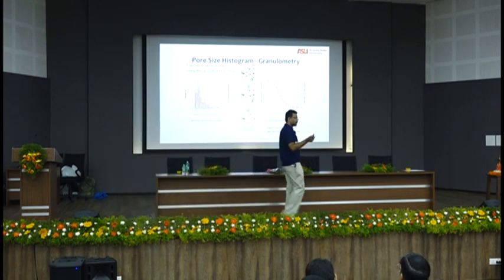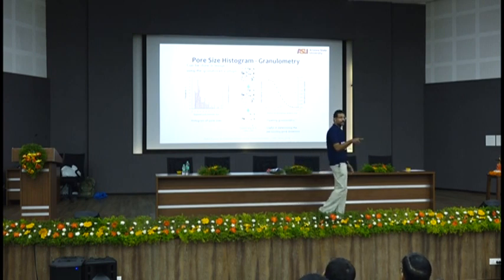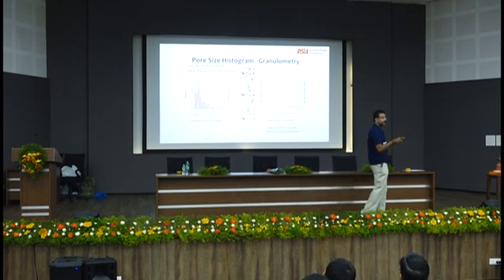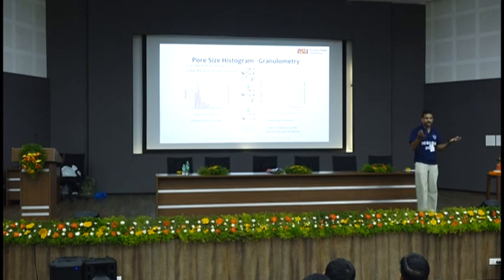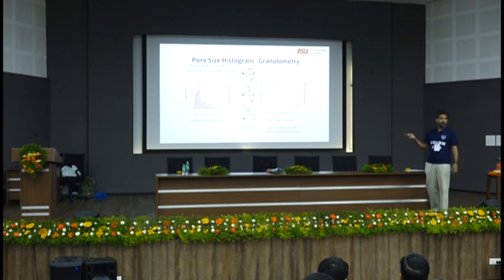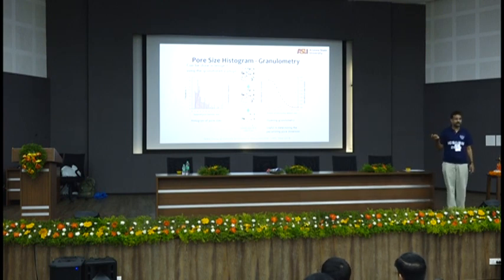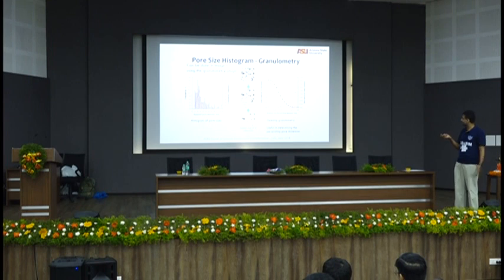And so one of the drawbacks of the MIP, what was the drawback of mercury intrusion porosimetry? The pores that are constricted, right? So the ink bottle pore effect. That could be overcome by using image analysis. So if you take an SEM image or multiple SEM images, you can do what's called granulometry, and I'll show you what that is, okay? So here is an image, pores and solids, right? You can open the images.